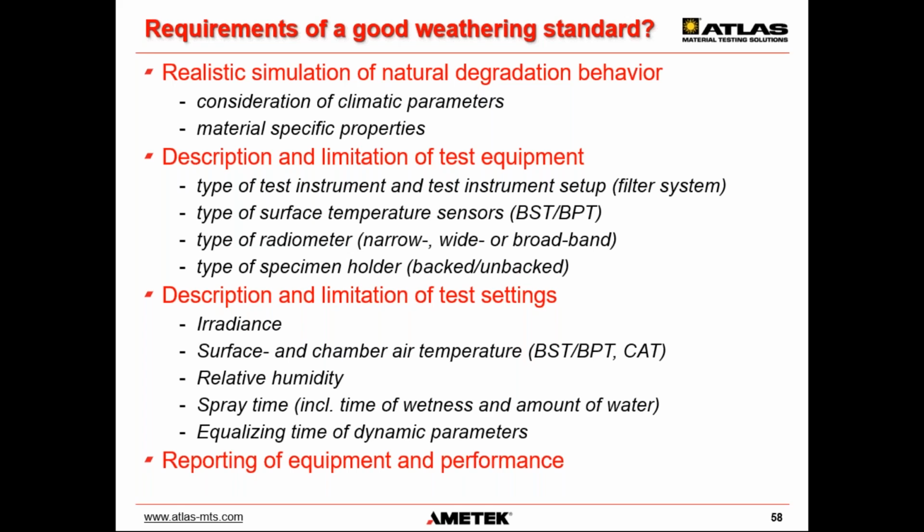Also, the description and limitations of the test settings should be specified to include irradiance, surface and air and chamber air temperatures, relative humidity, spray time, which would include time of wetness or the amount of water, and finally the equalizing time for the dynamic parameters.